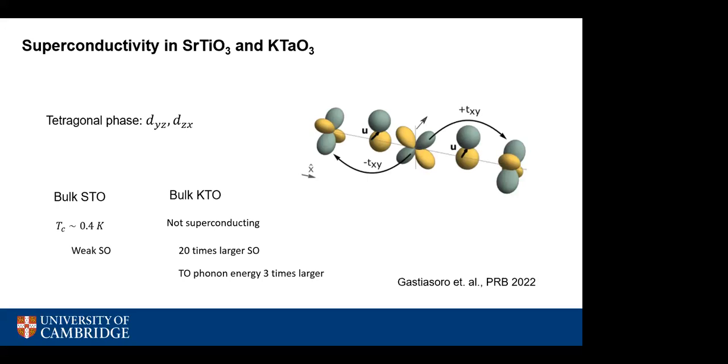No, I was saying that because you have larger spin orbit coupling, you're starting with, let's say, d orbital bands. The d orbital bands are very elliptical, t2g, right? Then if you put in spin orbit coupling, that mixes the dxy with dyz, and that makes it isotropic. That then decreases the density of states at lower doping. So it's like going from a quasi-1D, 2D band to a 2D isotropic, 3D band.